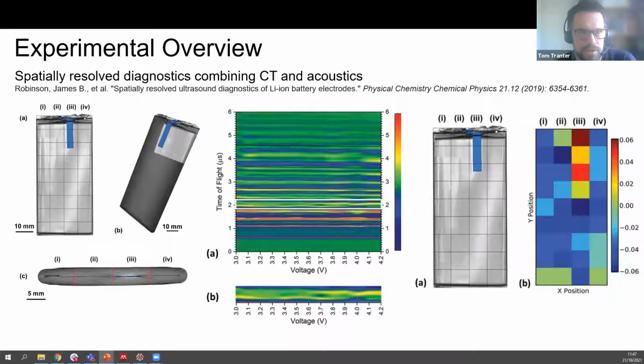Experimentally, we've done quite a bit. This was a study from a few years back where we essentially divided the cell up into different sections and placed a transducer at each one and monitored the response at different points. And you can see the effect of different macro level features, such as the tab placement, is very much affecting the signal quite greatly. It was one of these rolled designs, a prismatic cell, and you have sections in the middle where there may be better contact than in some other areas, and that also affects the kind of signal you get.